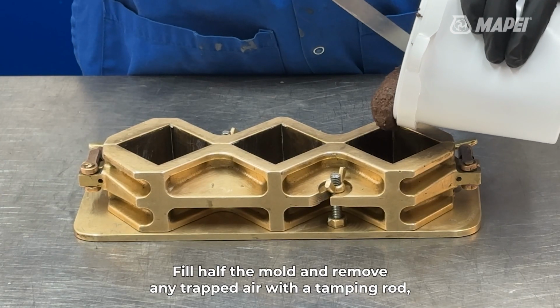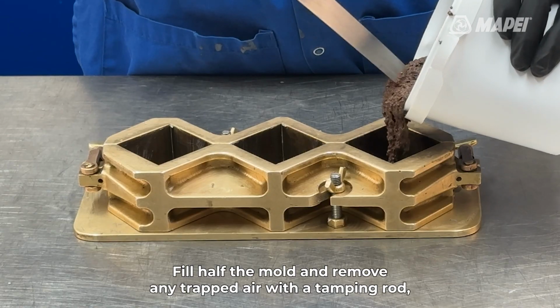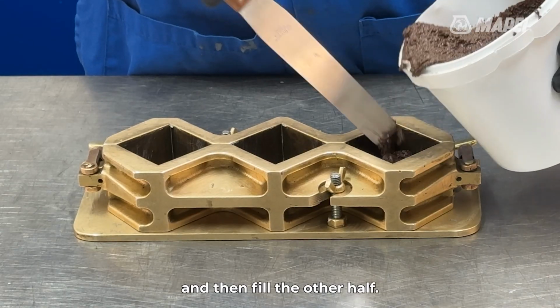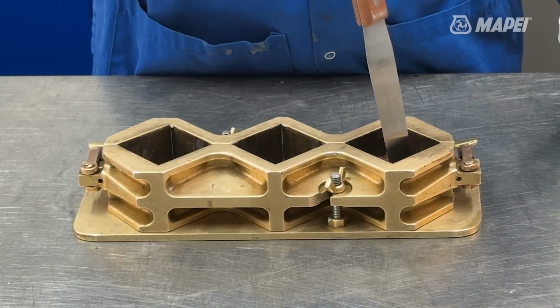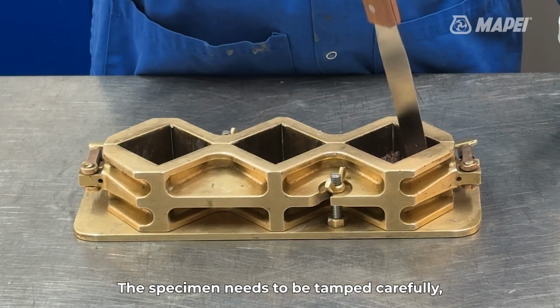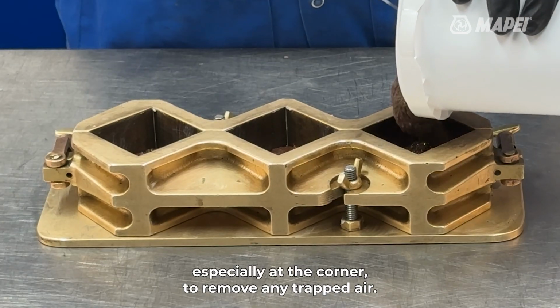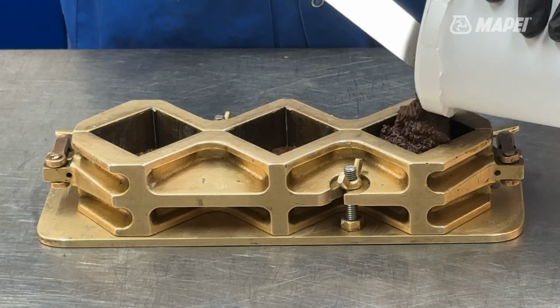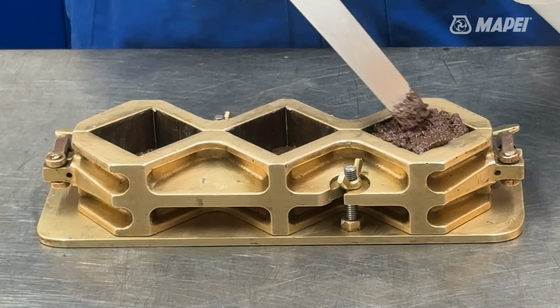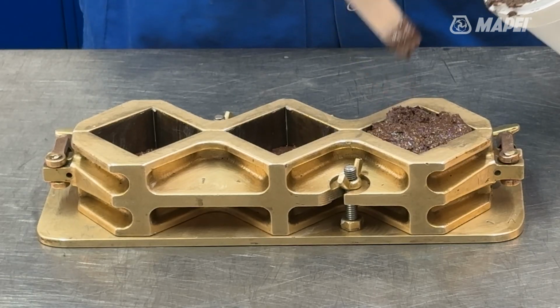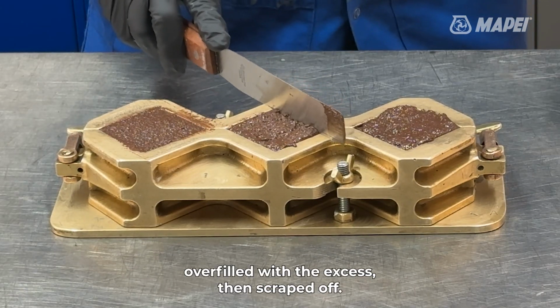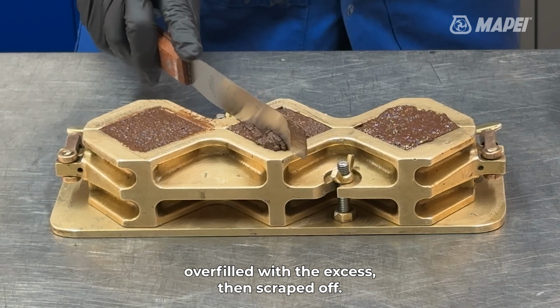Fill half the mold and remove any trapped air with a tamping rod, and then fill the other half. The specimen needs to be tamped carefully, especially at the corner to remove any trapped air. The mold should be slightly overfilled, with the excess then scraped off.